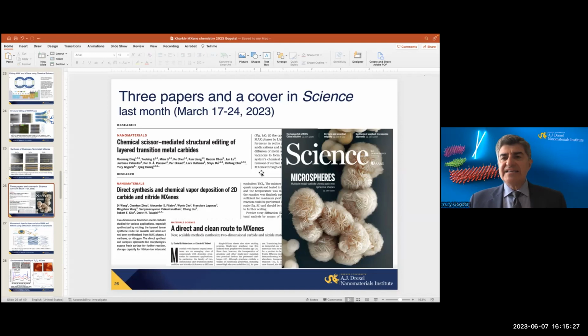And people either use, for light alloys like aluminum and magnesium, silicon carbide whiskers and others, which have their limitations, or try to use carbon, but carbon is not wetted by aluminum or magnesium. As a result, poor wettability creates problems with nanotubes and graphene, and they're very difficult to disperse. MXenes have good dispersibility. But the number of papers on metal matrix composites with MXenes is basically limited. I don't know, a dozen papers, probably less.